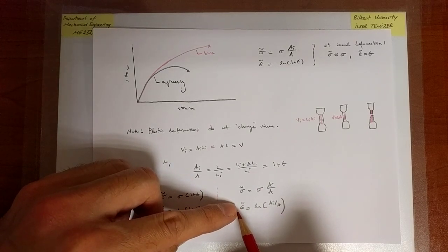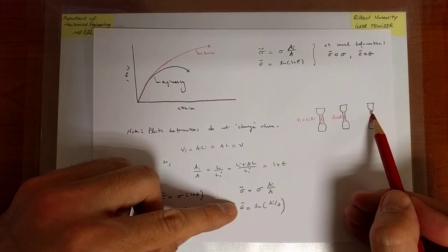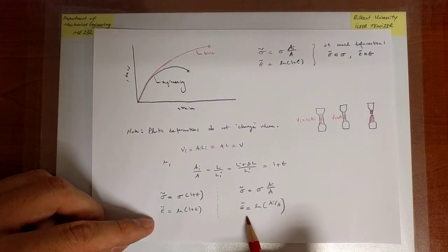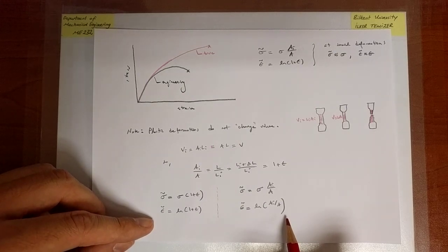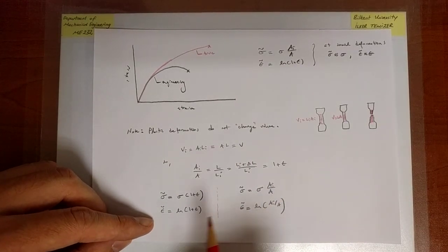It's also necessary to additionally measure the cross-sectional area during deformation. And if necking occurs, I have to measure the small area that is in the vicinity of the necking zone, which is very, very hard. So these relations are nice. They are valid all the way up to failure, but they are of no direct experimental applicability unless you have a good way to measure that cross-sectional area.